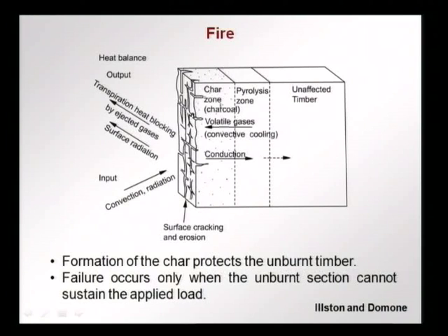This zone is what has burnt, a charcoal or charring zone is formed, and as the volatile gases of the timber that is being heated come out, there is some convective cooling. This part is cooled and protects the interior of the timber. There is some conduction, but again the charcoal is a poor conductor, so unless it cracks and falls off, heat does not conduct inside. There is a zone which is degrading, called the pyrolysis zone. This is the zone where the wood is degrading and going to catch fire and become charcoal.